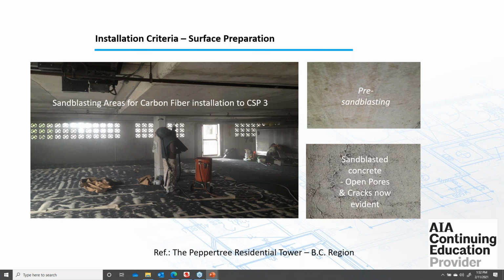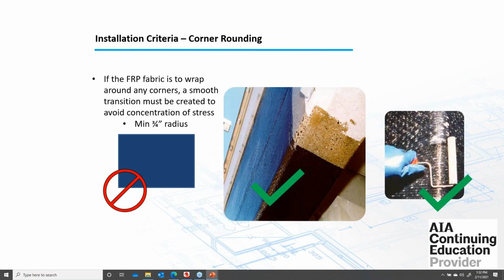One of the most used ones for vertical and overhead applications is sandblasting to CSP3. As you can see in the pictures on your right, sandblasted concrete shows open pores and makes many cracks evident. Next slide. If the FRP fabric is to wrap around any corners, a smooth transition must be created to avoid concentration of stress.